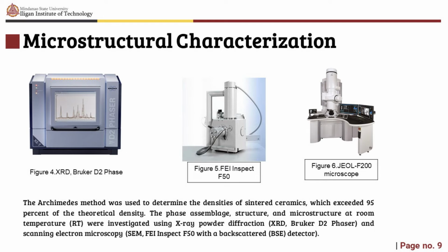Microstructural characterization. The Archimedes method was used to determine the densities of sintered ceramics, which exceeded 95% of the theoretical density. The phase assemblage structure and microstructure at room temperature were investigated using X-ray powder diffraction, which is XRD, Bruker D2 Phaser, and scanning electron microscopy using SEM FEI Inspect F50 with a backscatter detector.